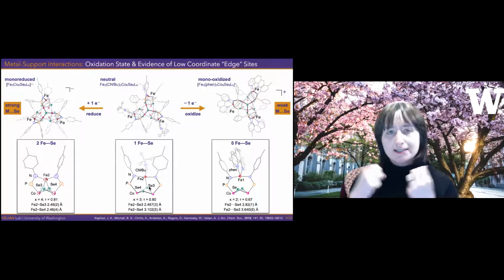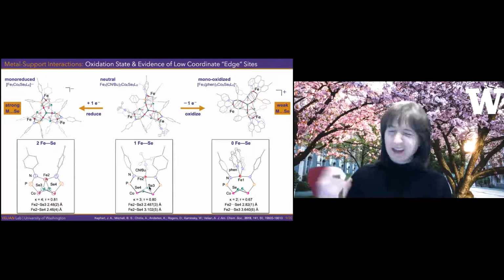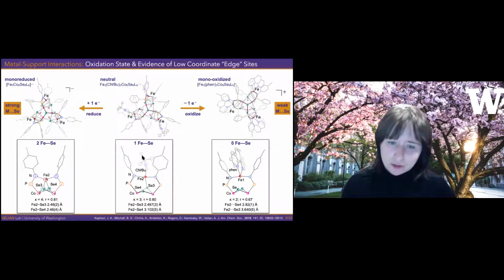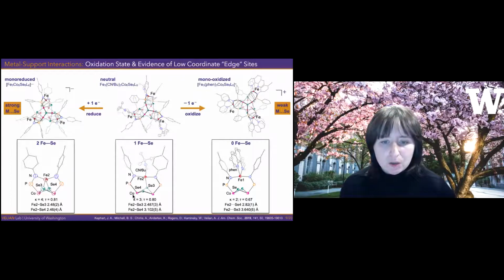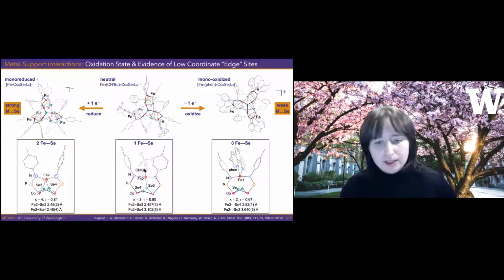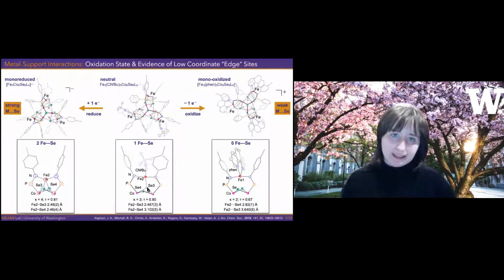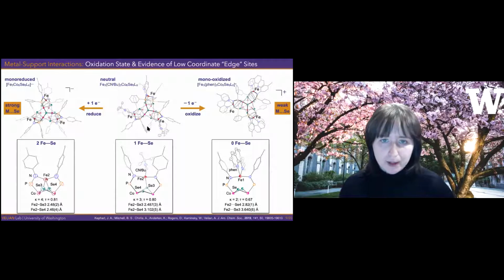So you don't want a saturated metal, because then it cannot engage with a substrate. So this was really encouraging to us because there was a substrate, isocyanide, coordinated to the metal, and at the same time the metal had one interaction with the surface selenium site. But not with the other one, okay? So it's only binding to one of the exposed selenium in that coordination pocket.